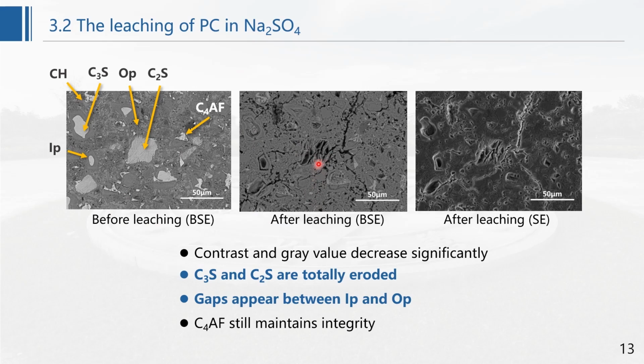It is worth noting that layered structures appear in the original position of C2S after leaching. Different from the phenomenon in deionized water, significant gaps can be found between inner product and outer product. C4AF still maintains integrity in the matrix.